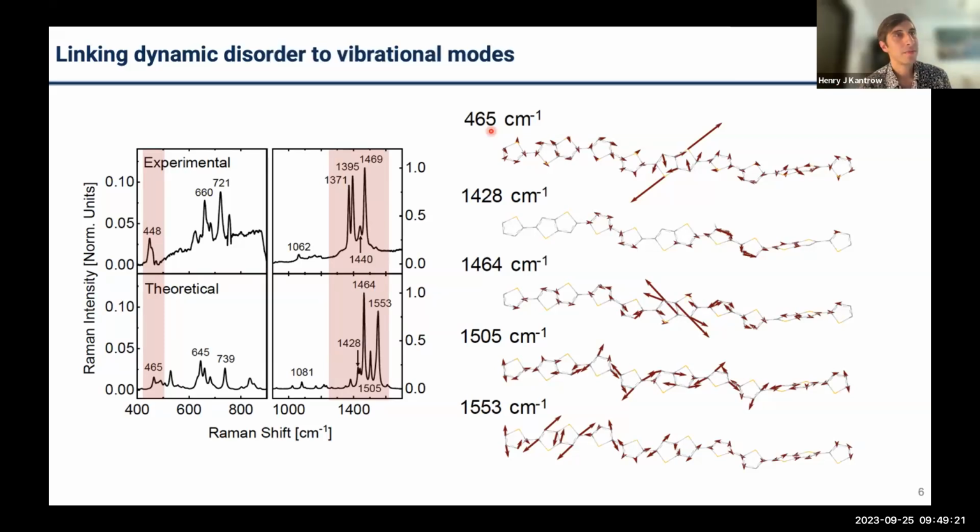Yeah, so first of all, the point that the inhomogeneous line width related to the static disorder should be independent of temperature, to me, more or less makes sense. If you have some distribution of local ordering of your polymer, as you cool down, you're just freezing those in place. And at 10K, you really have the same thing that you started with at 295K, some distribution of energies, right? Rationalizing that in terms of this dynamic disorder and its energetic barriers is something that I should probably think more about.